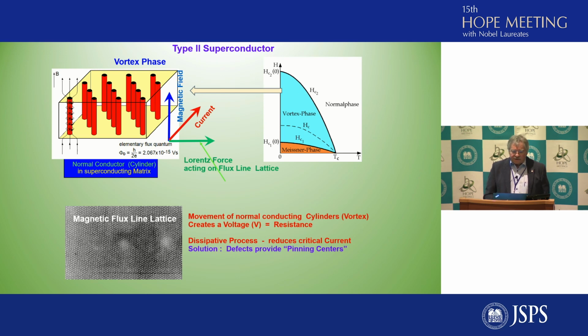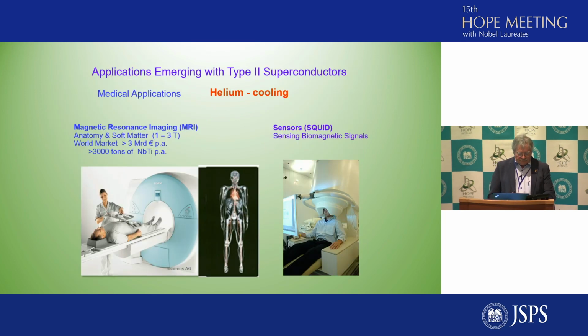But there were ways around this dilemma that magnetic field would destroy the superconductivity, because superconductivity in the type 2 superconductors is remaining still when the field is partially penetrating in form of such flux lines, which are normal in the center, but embedded in a superconducting matrix. So the material, despite the fact that a high current is passed and a strong magnetic field is applied to the superconductor, when a magnet is constructed out of them, the superconductivity still survives. So there were a lot of applications emerging with type 2 superconductors.